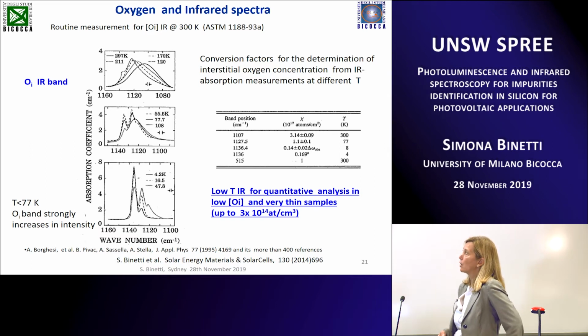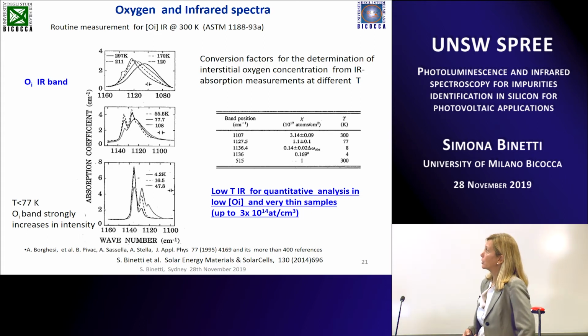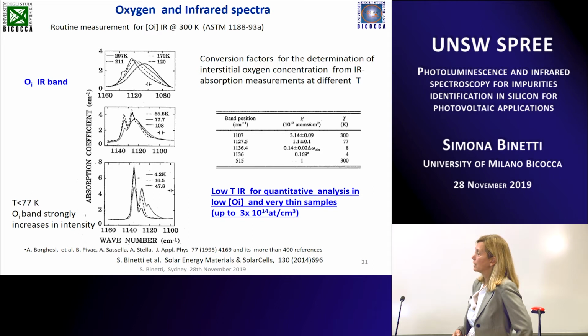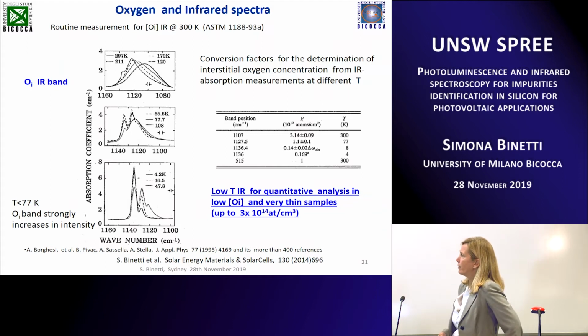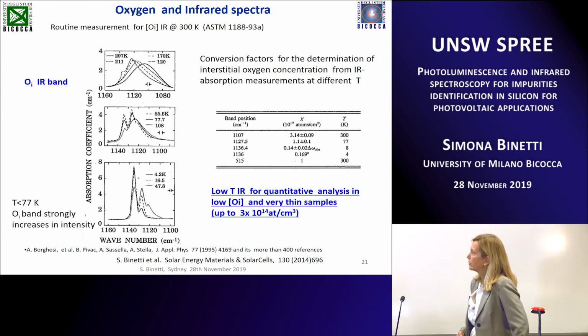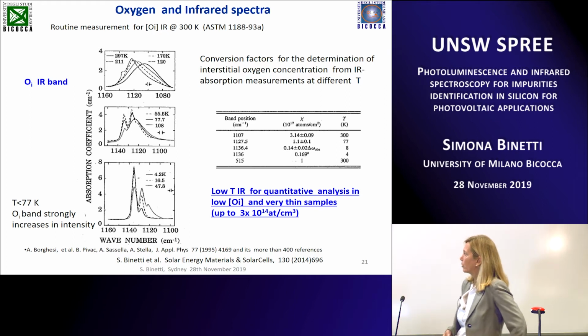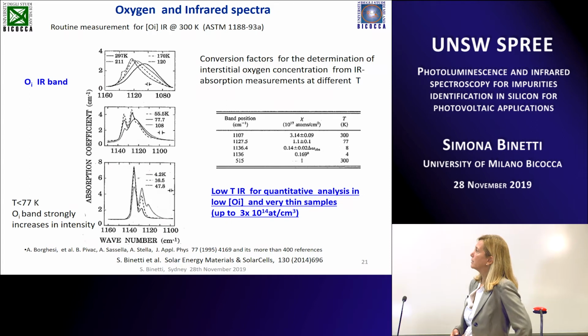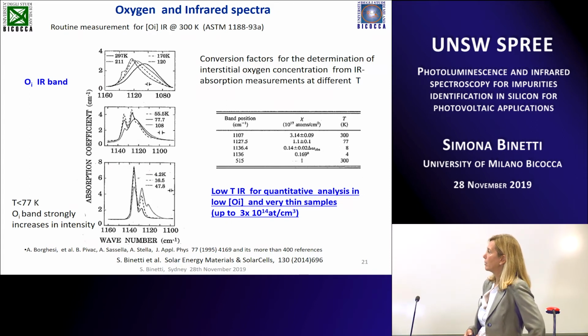And in this case you can detect oxygen up to 10 to 14, because when you go down with temperature there is a splitting of the band position, and it's also possible to see the isotopes of oxygen. By each band position a calibration factor has been calculated that can be used easily to quantify the oxygen in your material. You can find a lot of information in this very old review paper that was written by a colleague of mine. Professor Borghesi has been retired some years ago, but Adele Sassella is a friend of mine and is working with me in my department of material science, and did this very useful review many years ago.